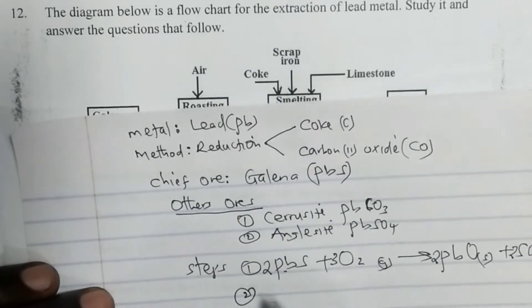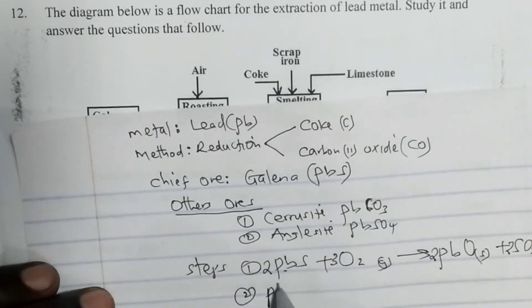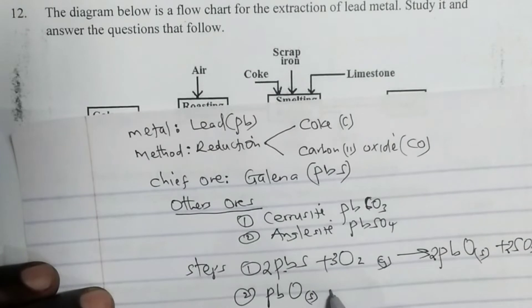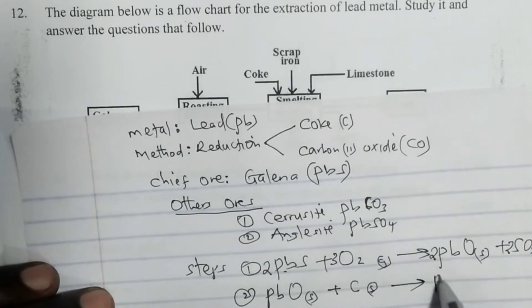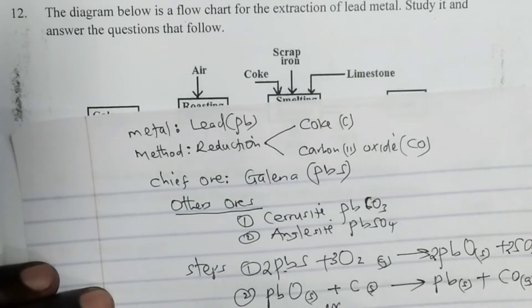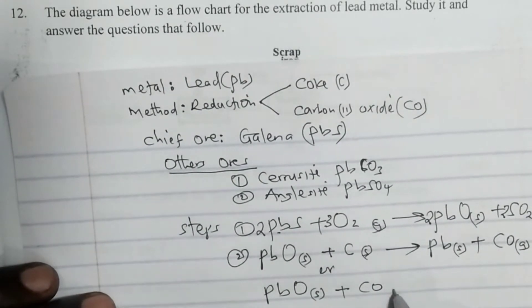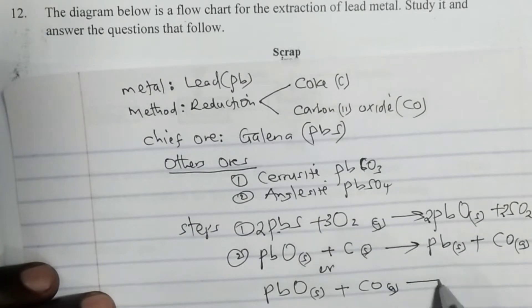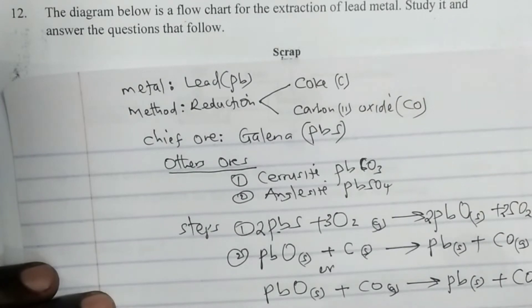Step 2, we take the lead-2-oxide, which is a solid, and reduce it by either coke. If we reduce it by coke, we get lead metal and carbon monoxide (CO), which is a gas. Or, we can also take the lead-2-oxide solid and reduce it by the main reducing agent, which is carbon monoxide (CO), and this reaction produces lead metal plus carbon dioxide (CO₂), which is a gas.